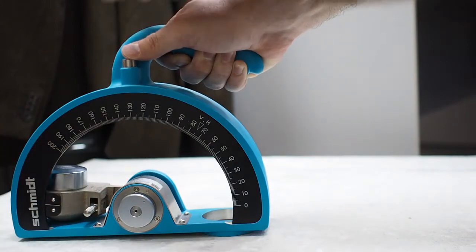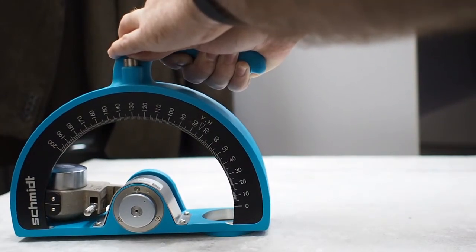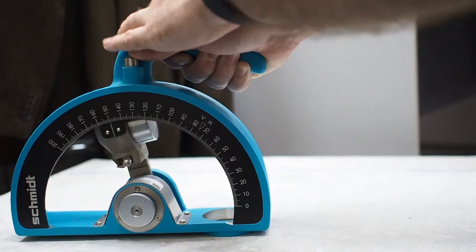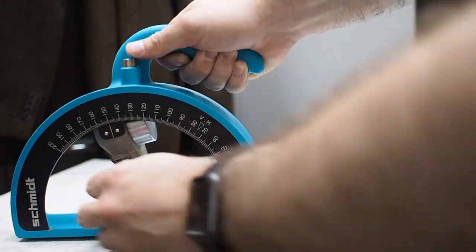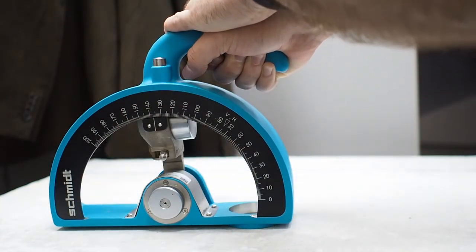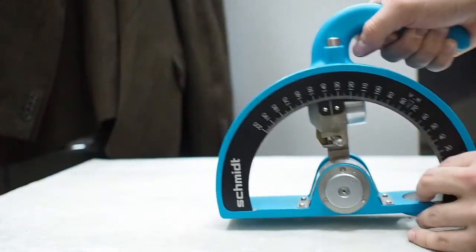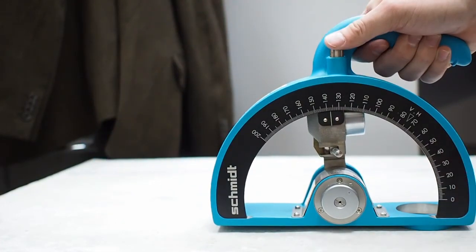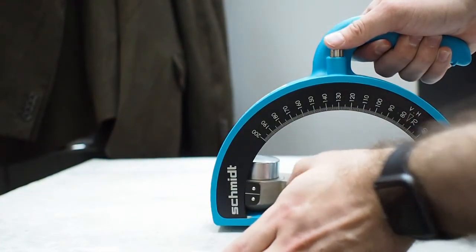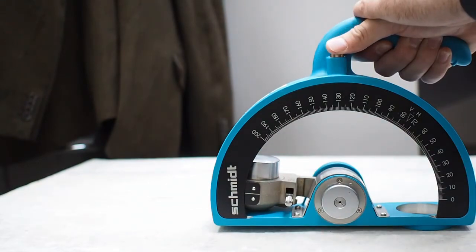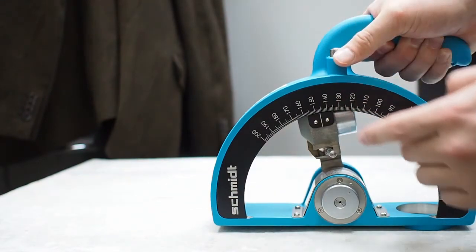So this one was about a 135 on the scale. I'll take a second strike, pushing firmly, striking about a 150. And it'll be the average of these results that will form our final test result. About 147. Sorry, 137. Then I'll complete the rest of the impacts.